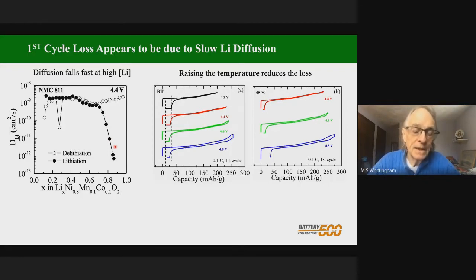So we're having very great difficulty in getting the last 20% of the lithium into the structure. And you can think of this just as if you're in class in person right now. You're in a large lecture hall, and 75% of the seats in that lecture hall are filled in a random manner. To fill in the rest of the seats, which invariably are in the middle, everybody has to move. So this is the same in this lithiation. For these last lithium ions to move in, all the lithium ions in the structure have to go in a more of a close pack configuration. And this is what's causing the issue here.